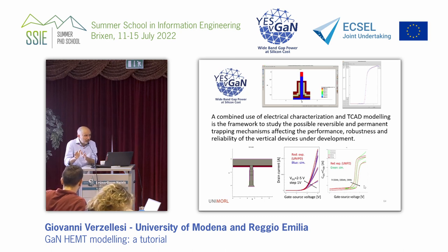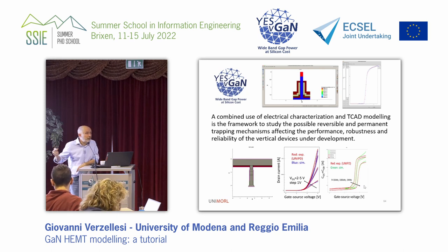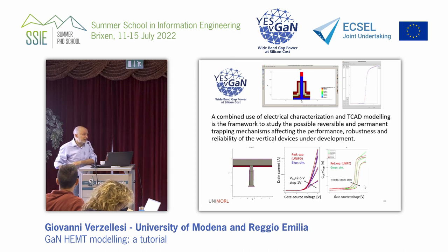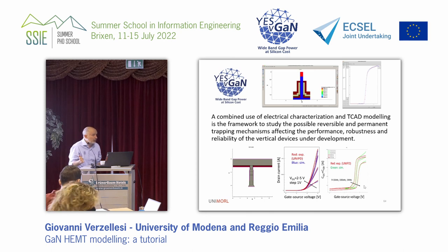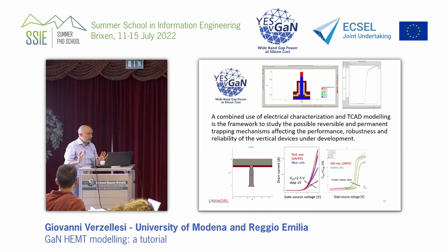Okay, in that case we had to, because we try to simulate electron injection from the substrate into the nitride layers. For all the simulations I have shown today, basically the region under the carbon-doped buffer, the carbon-doped buffer is completely taken into account within the framework of a dominant acceptor model for carbon, but all the layers under the carbon-doped buffer are basically assumed to be equivalently taken into account by an oxide layer, or an aluminum nitride layer corresponding to the nucleation layer and part of a substrate, depending on the case.